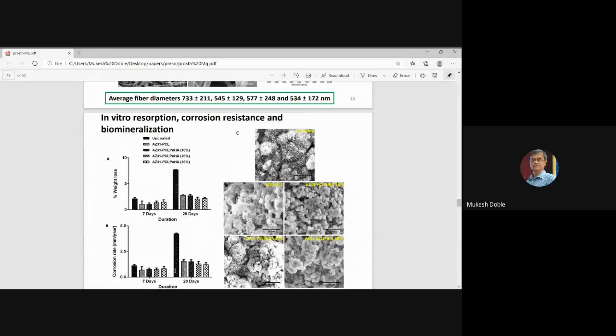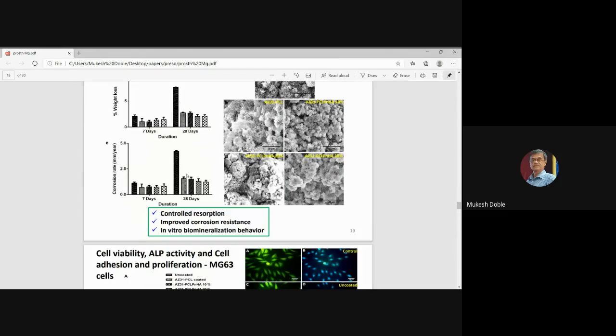And then we are looking at the biomineralization, resorption of the product. Different products which we have, with different amounts of hydroxyapatite, 10%, 20%, 30%, as you can see in this data. And then this is without hydroxyapatite, just the polycaprolactone alone. And this is uncoated on the top. So this is 7 days weight loss, and this is 28 days weight loss. So you can see the uncoated surface, a lot of weight loss, even 10% weight loss in 28 days. But the coated surface is able to control the weight loss. Okay, and we can see the in vitro biomineralization, as you can see from the scanning electron pictures.